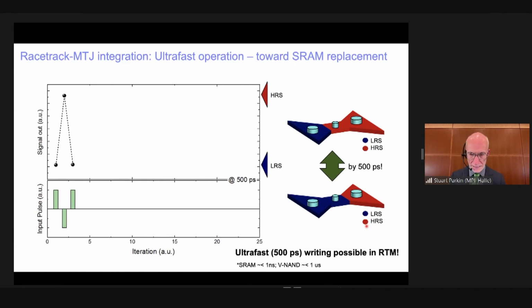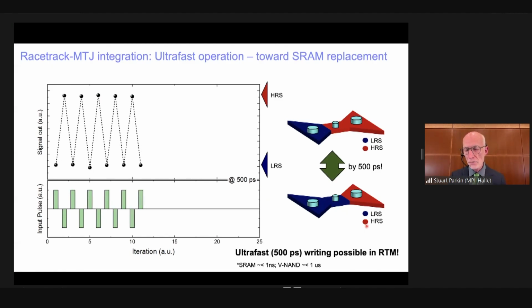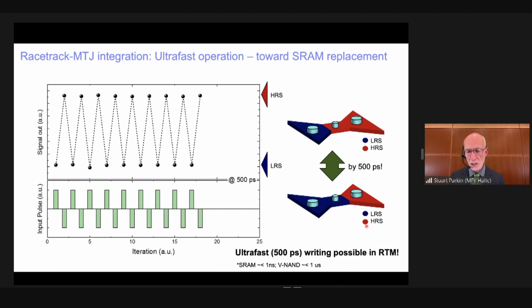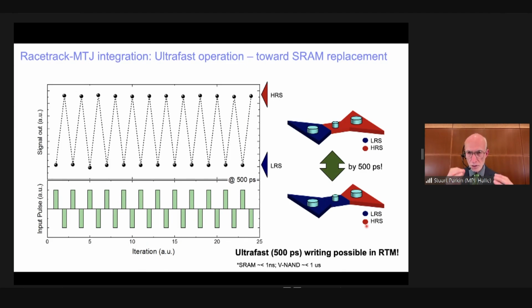We've also demonstrated that if we incorporate a tunnel junction reading device into a short racetrack, we can move a single domain wall from one side of the racetrack to the other, detect where it is, and we can do this in speeds of less than 500 picosecond. This is extremely fast. So we can build a single domain wall racetrack, which has a performance that is as good as the fastest charge-based memory today, static random access memory, but would have a smaller form factor and would be more reliable and, moreover, would be non-volatile. It retains the state without the need for current that would be needed in an SRAM, static random access device.